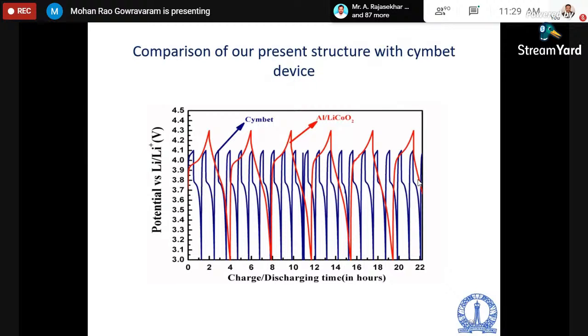Okay, good. So we tested this battery. It was a rechargeable battery. It gives you 55 microampere hour per centimeter square area. This is what we have also quoted now. And within less than 2 days, its capacity dropped drastically. So we heated it in the oven to 120 degrees and tested. It regained its electrochemical activity, but the capacity was no longer 55 microampere hour. It had reduced. So we analyzed what the reason for this was, then came to a conclusion.